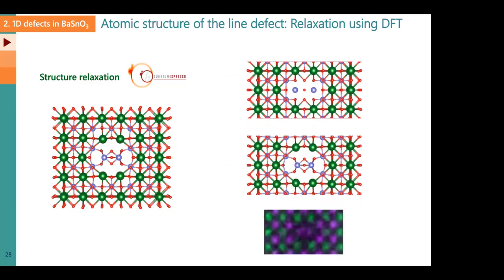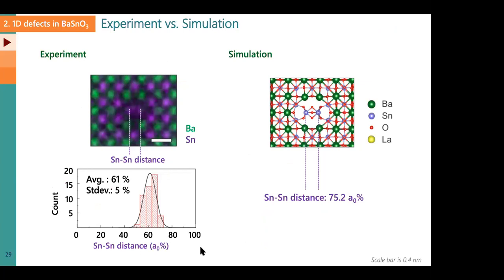Here it is. In this image, I put all of the atoms together: green is barium, purple is tin, and it basically correlates one by one with this theoretical data. When we measure the distance, it's almost perfectly matched what we observe in experiment. Here we have 61 and there is a 75. Just maybe a 10 to 15% difference, but that's not a big deal among friends.